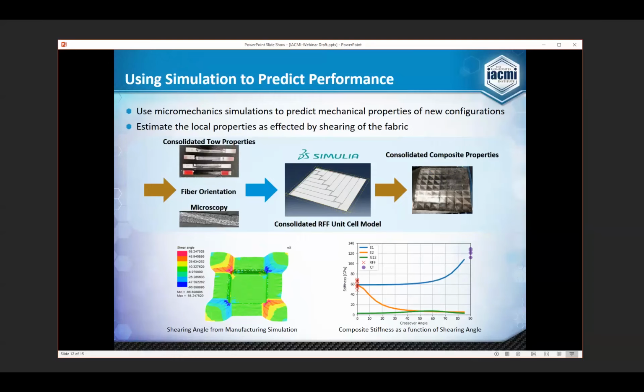One other thing we can point out is because in the RFF system we don't actually weave the toes, we can start off with different crossover angles of our toes. So our warp and weft don't have to be orthogonal to each other anymore. We can have the warp and weft angled at 45 degrees to one another, at 60 degrees, and we can optimize that initial crossover angle to get better part performance from that. And that's something we can explore with the model as well.